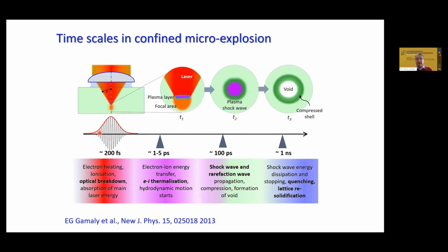So what happens at high intensity in your focal spot, you can drive your transparent material, you can ionize it and create free electrons, which are helping you to absorb more light in a very thin skin layer. And this is energy which is absorbed later driving your modification. So the light is already gone. Light is only sub-picosecond, and this evolution of modifications is happening later. And the most violent and largest modification you can think you can write inside the volume of transparent material would be a void. So this was our initial interest. Can we modify material very strongly, having very well-defined voids inside transparent bulk volume?